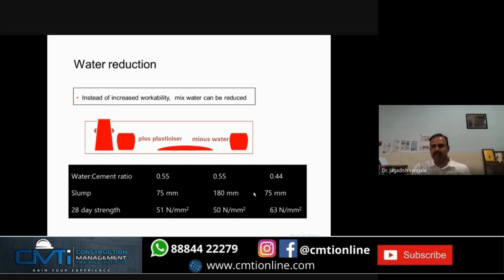The first case slump and the third case slump are the same, but by reducing water, adding admixture or superplasticizer, you are reducing the water cement ratio. Thus, you are getting more strength. You know Abrams' law, water to cement ratio to strength. When water cement ratio increases, strength decreases. You are reducing the water cement ratio, and your strength is increasing by adding superplasticizer while maintaining the workability.